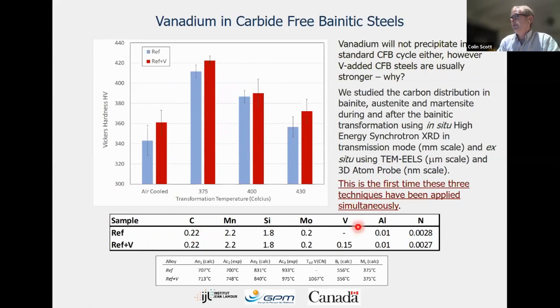So these are the grades we'll talk about today. 0.2 carbon, 2 manganese, 1.8 silicon, without vanadium, and with vanadium, 0.15 in this case. Very low nitrogen. We don't want vanadium to precipitate, so we don't add nitrogen here. This is called the reference alloy. This is the reference plus vanadium alloy, ref plus V.